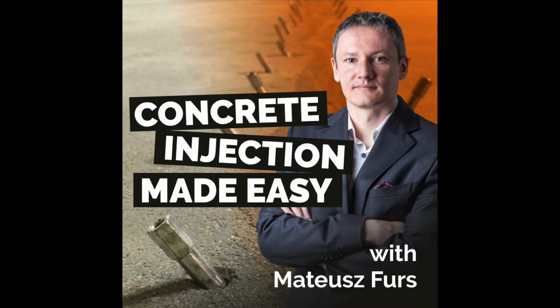A top-line similarity of PU and EP is that both will fill and seal cracks and thus make them watertight. Both prevent concrete and reinforcement corrosion. But epoxy has the added feature of structurally bonding the concrete sectors together and can restore the strength and structural characteristics of the concrete. At least every single TDS I have read says so. TDS? Technical Datasheet. This last factor often guides the decision-making process of the engineers designing the remedial construction to go for epoxy rather than for a polyurethane solution.